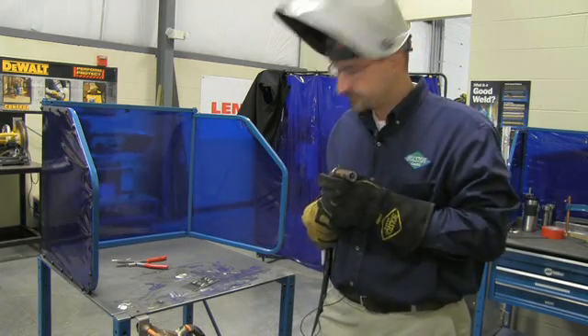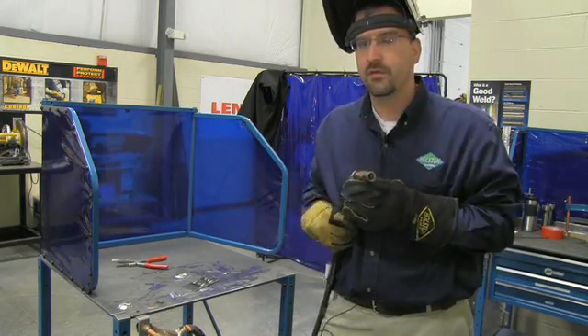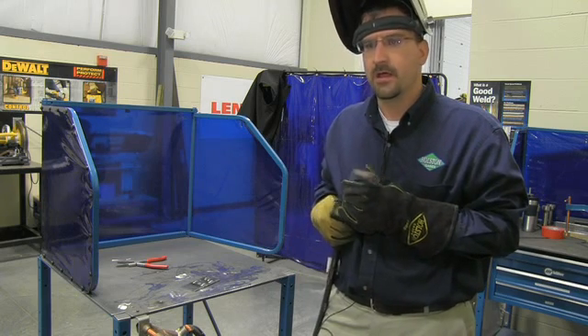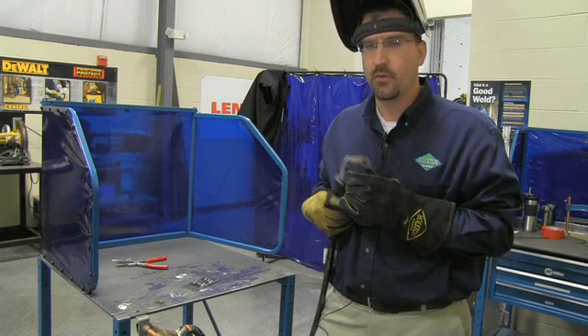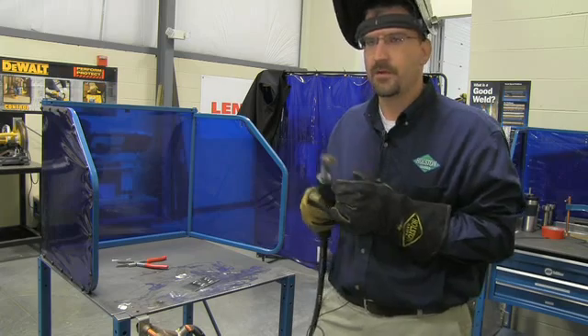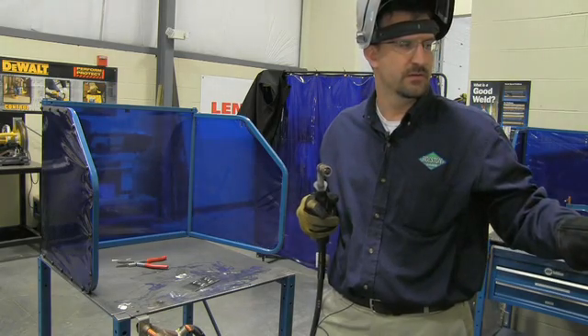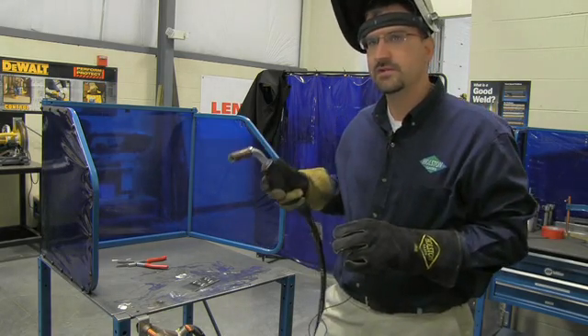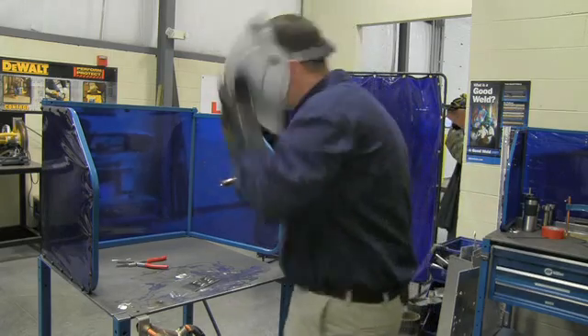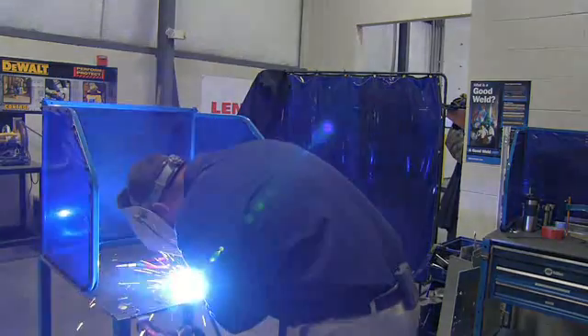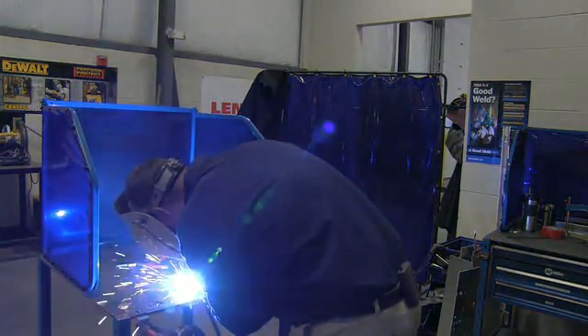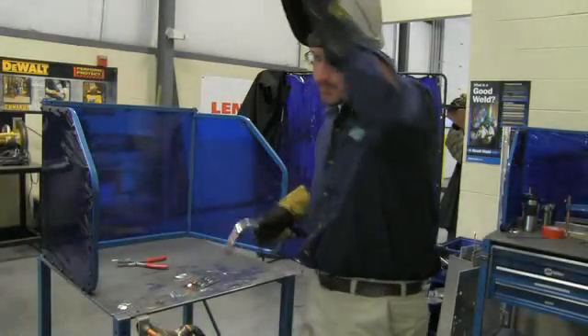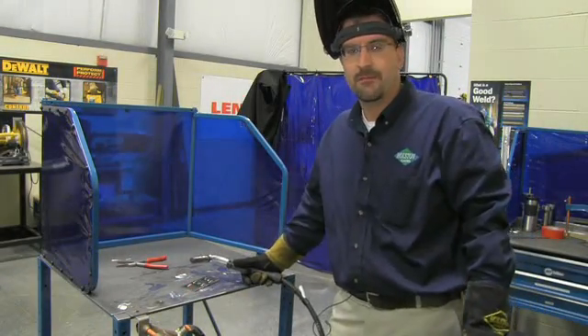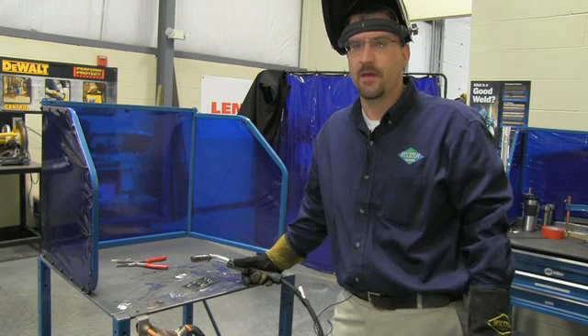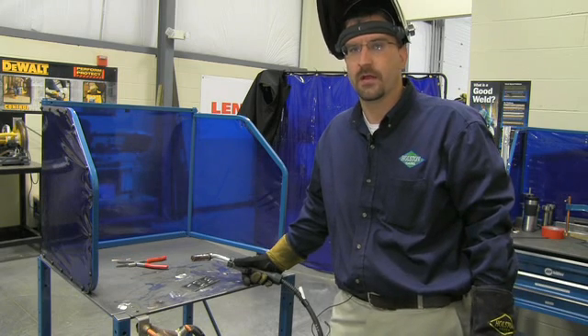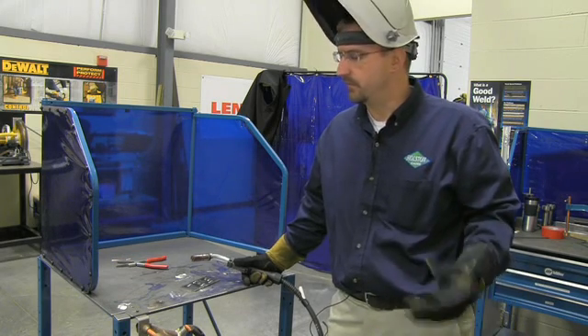The last thing to check is going to be the voltage. Make sure the welding parameters are set properly. A lot of times if the voltage is set too low for the wire feed speed, you'll get stubbing. So I'm going to demonstrate with a little bit higher voltage. I'm going to demonstrate what it should sound like on a good arc start. So you can notice that there wasn't any stubbing, the arc fired immediately, and that was because I used a short stick out to start the arc, and I have my parameter set properly with a good ground lead.